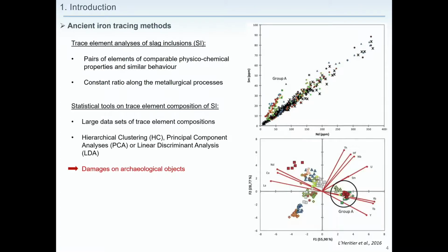In addition to this trace element analysis, some statistical tools are more and more used to improve discrimination on large data sets of trace element composition. Here is an example of principal component analysis, which shows that for the same samples, it allows better discrimination of the different sample groups. Even though it has already proved very efficient, the problem of analyzing slag inclusions is to find the slag inclusion, and so we may have to cut the samples, which could be quite problematic for museum pieces, for example.